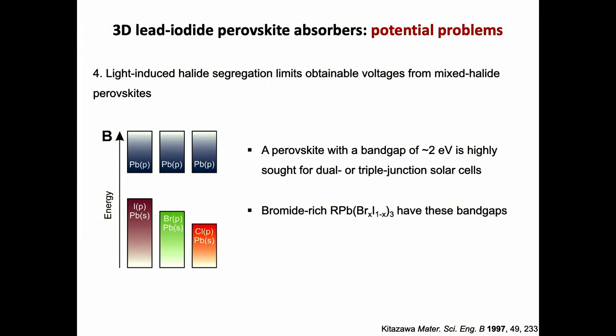The third problem we have tried to address in these materials is actually one of my favorite phenomena in halide perovskites. I think scientifically it's extremely interesting, though technologically it's not good. So here I'm showing you a very simple diagram that shows how the band gap of a halide perovskite changes based on the halide you use. So if you use chloride, you get a big band gap. If you use iodide, you get a small band gap. And bromide gives you an intermediate value.